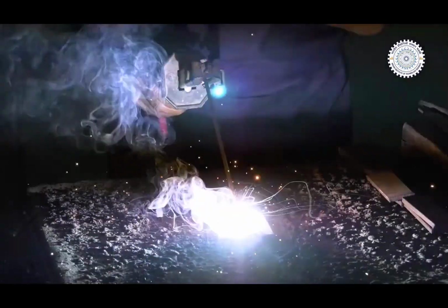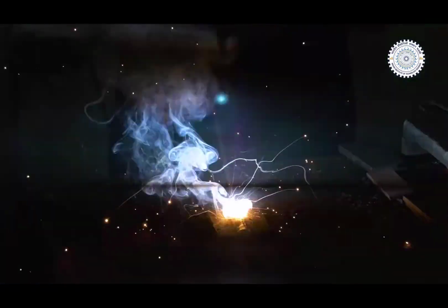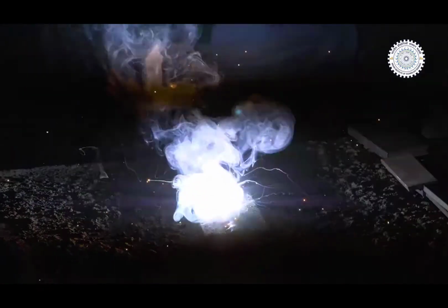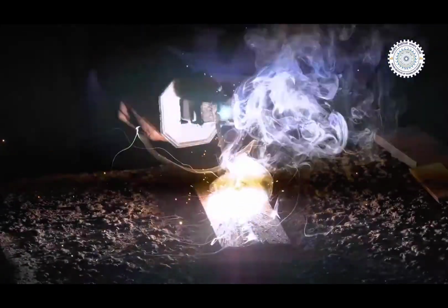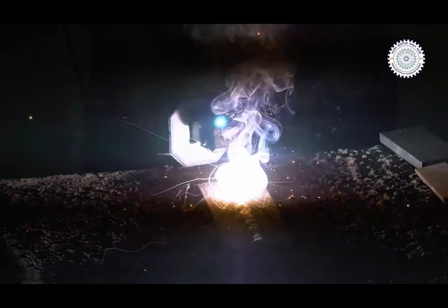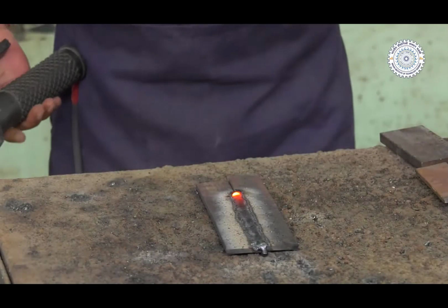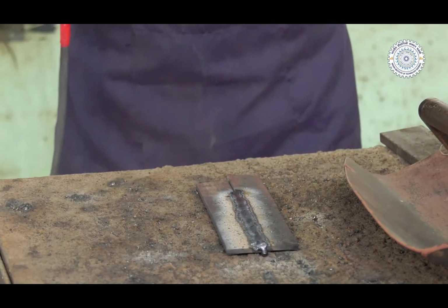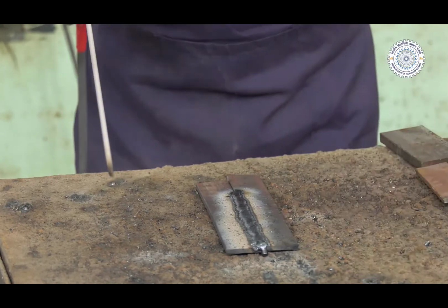So here, in a very controlled way, the arc is being moved along the weld line so that there is proper deposition of the molten metal as well as through-thickness penetration. The process is quite fast, but it requires a lot of skill in order to manipulate the arc, control the speed and the movement of the arc, and avoid the sticking of the electrode with the workpiece. So the welding current and the speed of the movement of the arc determine the amount of heat being supplied during the welding. So this is how you can see the weld is done, and here we have replaced the electrode,